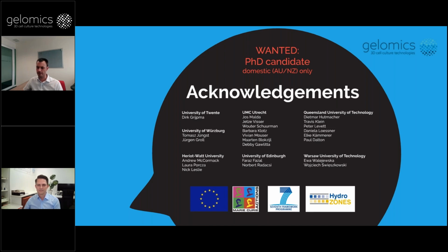And I think generally in research, people stick too long with what they're comfortable with and used to. That photo initiator was only used because in one paper back in 2000 in the Bryant Anseth group, Stephanie Bryant just tested a few off-the-shelf initiators. None of them were intended to ever be used with cells. One of them turned out to be quite reasonably water-soluble and less toxic than all the rest. After that, people just kept using the Irgacure, but we also don't really know the long-term effects of the UV. Even if the viability is good after 24 hours, we don't know what it does to DNA damage.